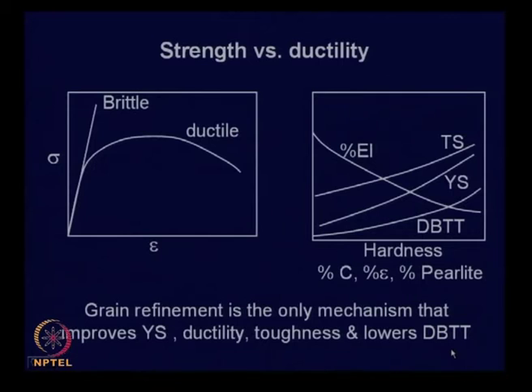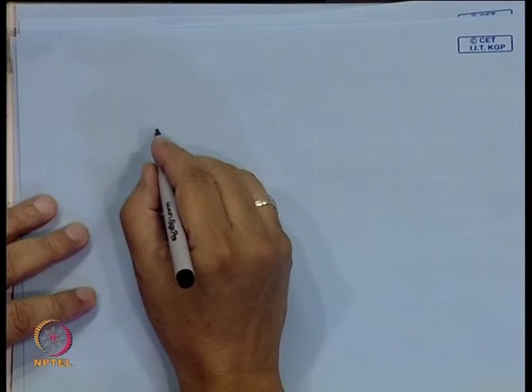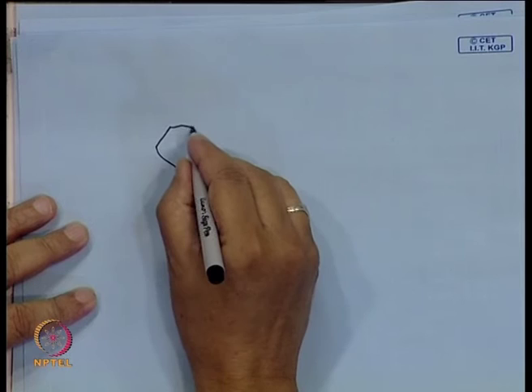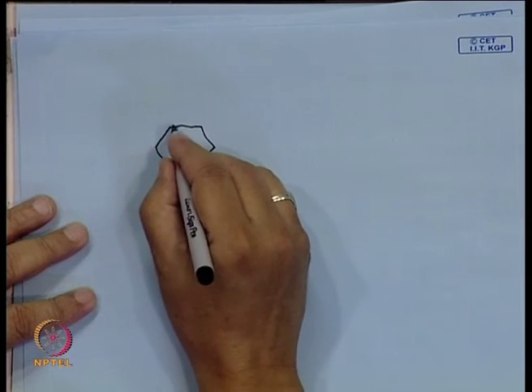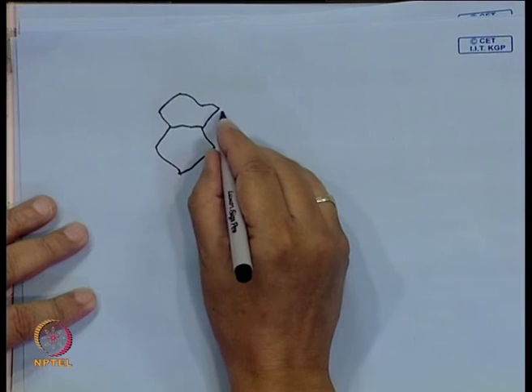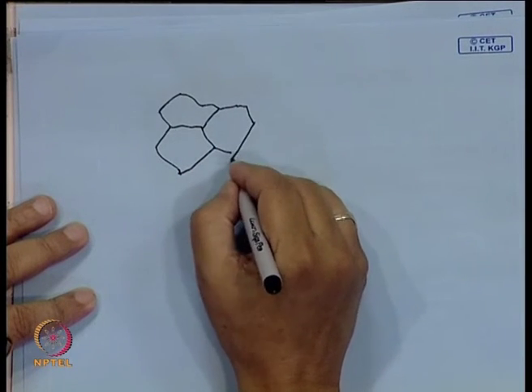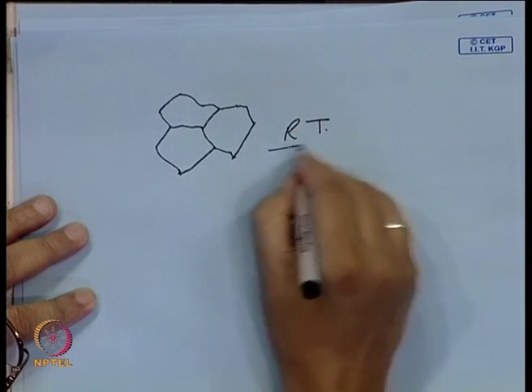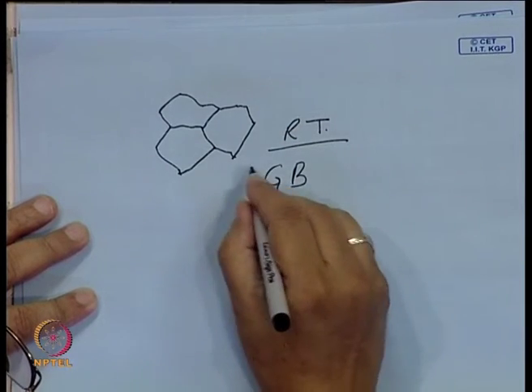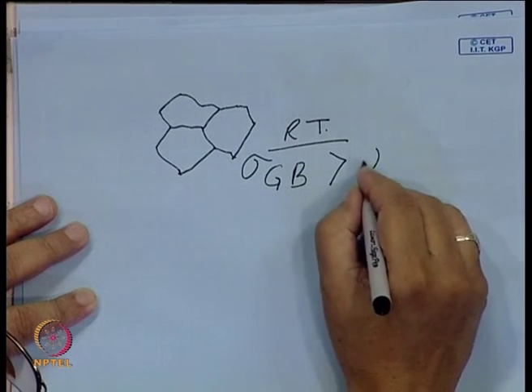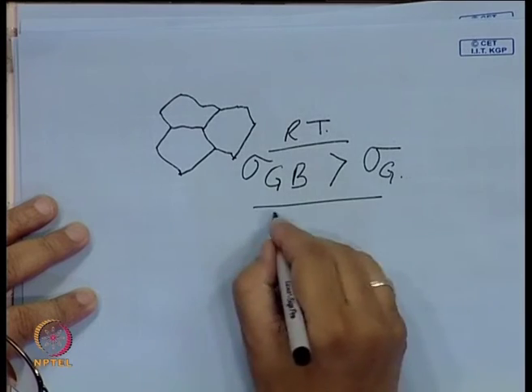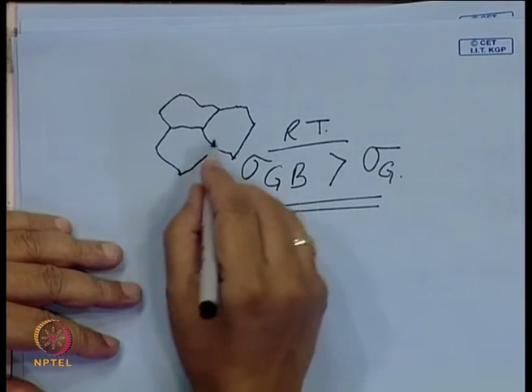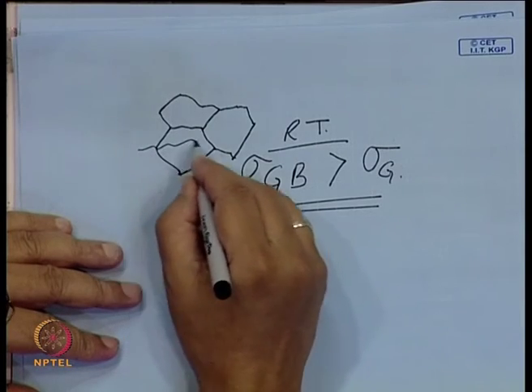Normally, whenever a fracture takes place, there are certain crack paths which are favorable. Usually at room temperature, we find the grain boundaries are stronger. Normally, at room temperature, the strength of the grain boundary is greater than the strength of the grain. So if a fracture takes place at room temperature, it is more likely that the fracture takes place through the grain.